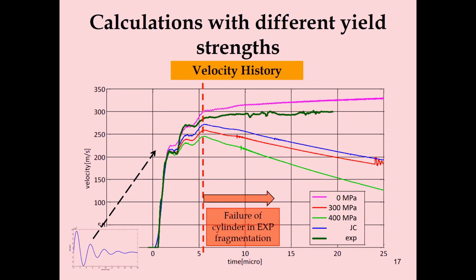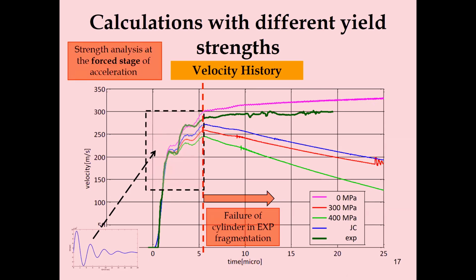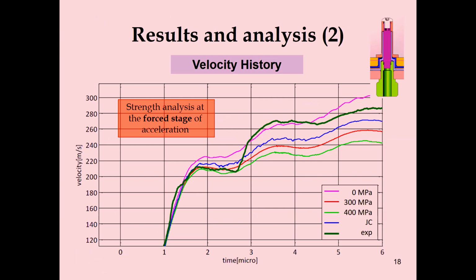So the important part of this technique is looking at the initial stage of acceleration, okay? And this is very important because we're looking at the forced stage of acceleration. Most of the analysis which is done on rings or cylinders is looking at the free flight stage, which is more here on the right. When you look at the forced stage, you can enjoy the benefit of the very fast rise time of the pulse current generator. And that's how we're reaching very high strain rates in relation to other techniques which are looking at the expansion of rings or cylinders.